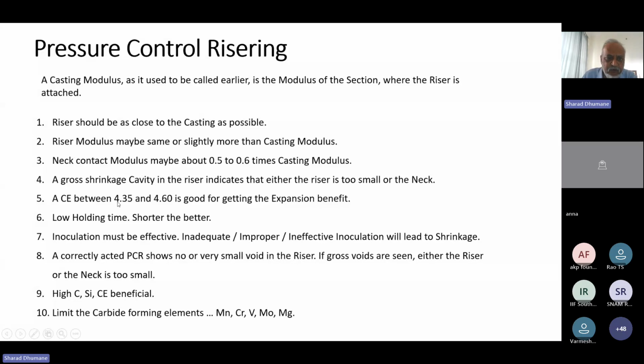A carbon equivalent between 4.35 to 4.60 is good for getting the expansion benefit, because more graphite is available. But as we have seen earlier, as the carbon equivalent increases, the solidification shrinkage also increases. So we have to do a balance, and carbon equivalent close to 4.35 is, I would say, an optimum carbon equivalent where you get the benefit of fluidity as well as lower solidification shrinkage.